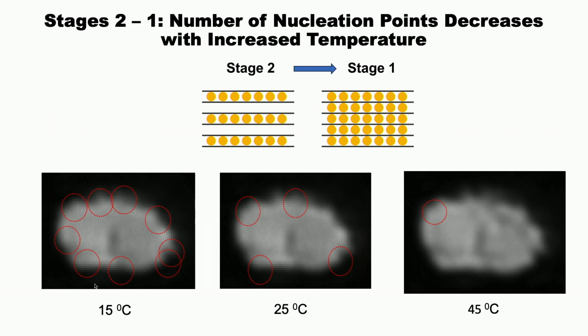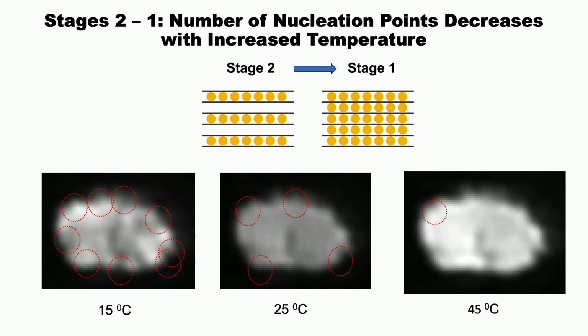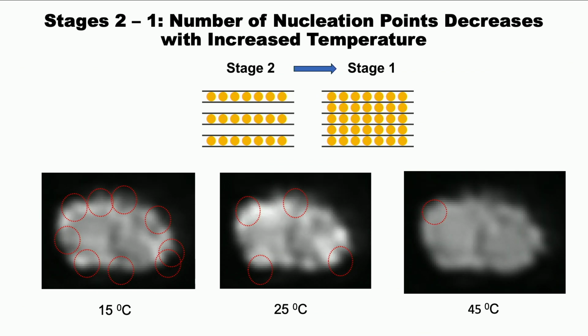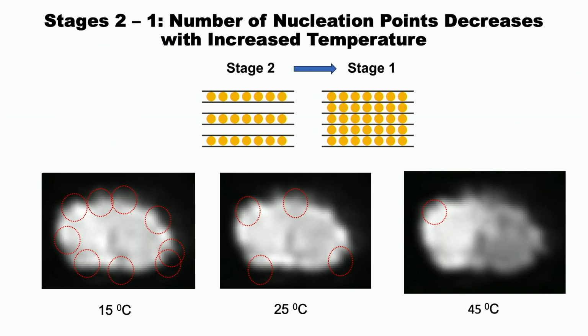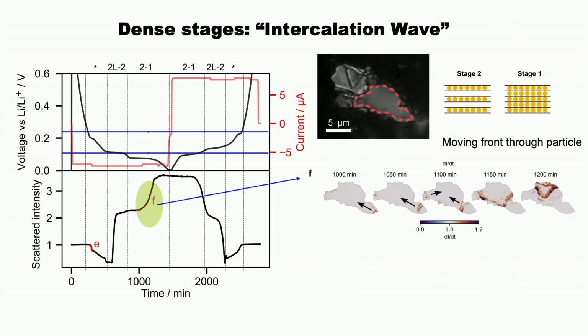So what can you do in terms of using this information? This movie is a new one that never works. So you can explore nucleation. This is at low temperature, and if you watch, you can see that there are sort of multiple nucleation events. If you go up in temperature, if I get the movie to work, there are fewer nucleation events, but actually at the highest temperature, you can see it's just a single nucleation event. And so the differences in the transport of the lithium ions as a function of temperature have a significant impact in how these materials operate.